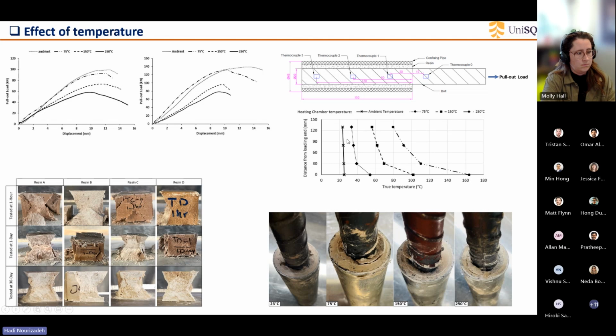As you see, higher temperature can cause an increase in the temperature along the encapsulation lengths. But when we go deep into these encapsulation lengths, the temperature drops significantly. By conducting the pullout test, we realized that the type of resin can significantly affect the behavior of these bonding materials. For example, here we use bonding agent A and bonding agent B. We increase the temperature from ambient to 250.